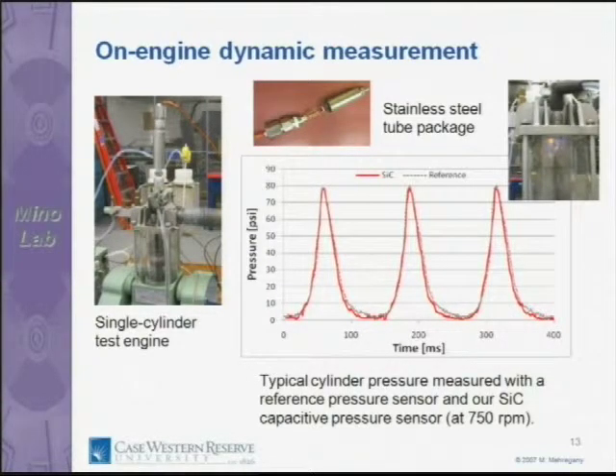I'm going to skip these details and just show you that this sensor, the silicon carbide sensor, which is the red curve, was tested, essentially packaged in a stainless steel tube by Li Chen, and tested in a test engine in mechanical engineering department. They have a test engine that runs alcohol as a fuel, and they actually have a reference research sensor. And you see that our sensor tracks the research sensor very well, but it has better sensitivity at very low pressure. So again, it sort of verifies that you can fabricate these devices, put them in a combustion chamber, and measure the change in pressure.